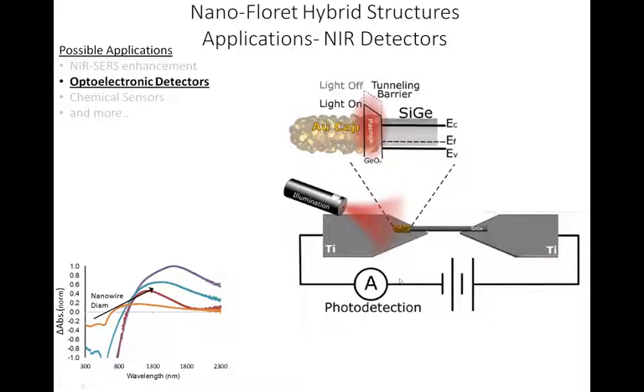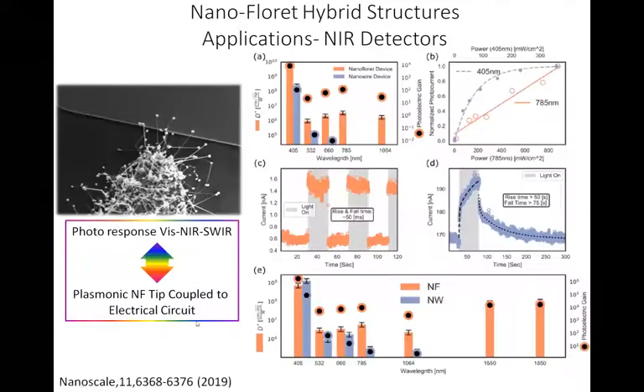Now we can put a potential across and check the conductivity as a function of illumination in the near IR. This is exactly what we did. This is how it looks in reality. So you can see the tip, which is a titanium electrode and counter electrode, and these nanoflorets with the metallic tip bridge over this gap. And now we measure the currents as a function of illumination, and we compare nanowires to nanoflorets. So because of the time, I will make it really short. Let's concentrate here on panel E.